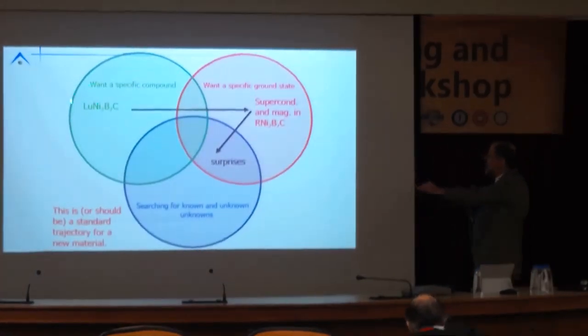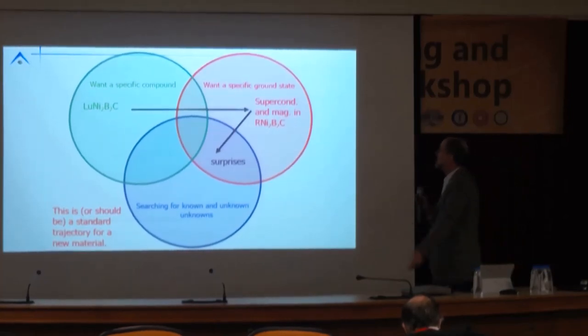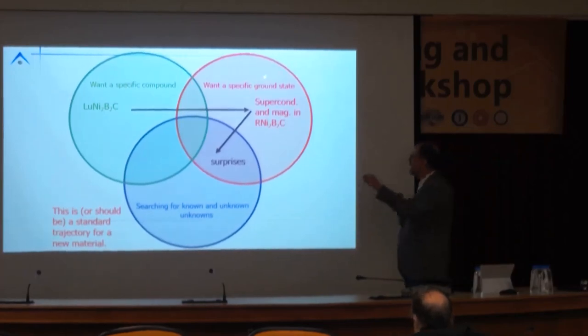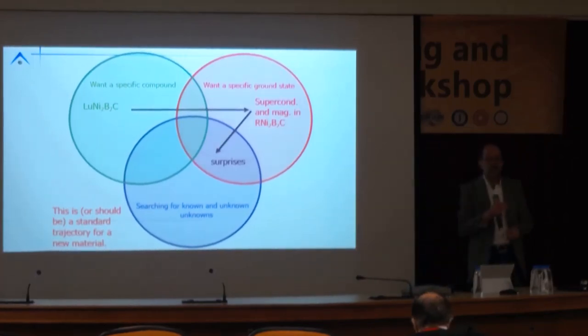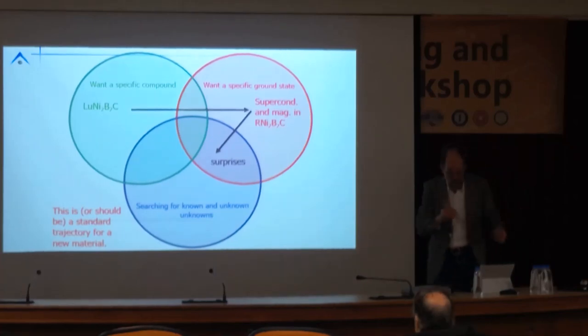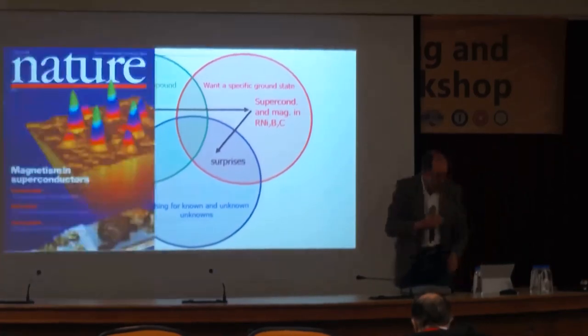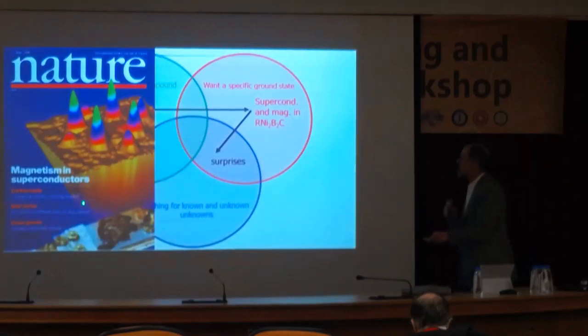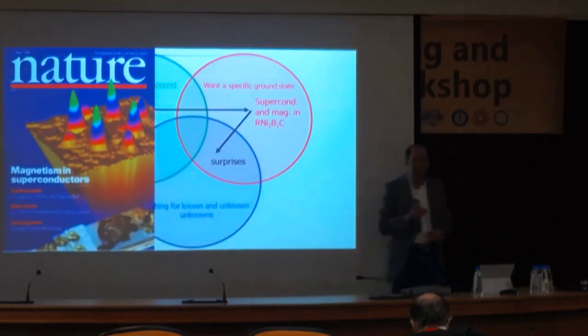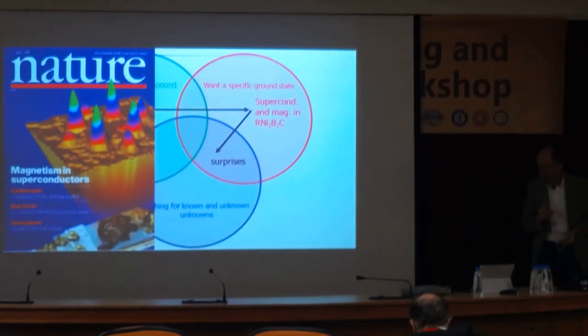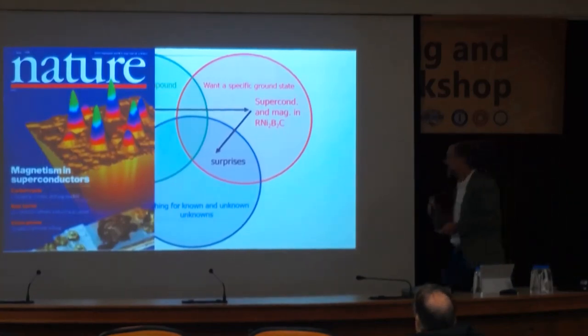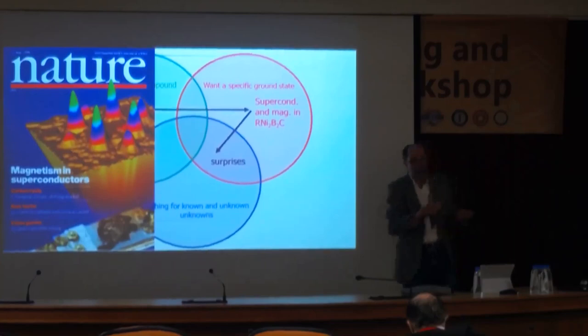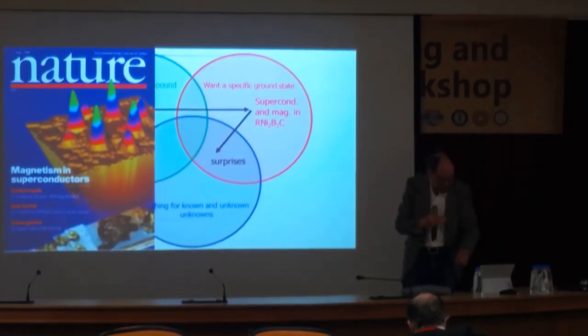So, we have a progression. We wanted a specific compound, lutetium nickel boron carbon. Once we had it, we could generalize and look at the interaction of superconductivity and magnetism in all of these materials, and as often is the case, this can lead to surprises or unknowns. In this case, the unknown was the discovery that in these materials, if you apply a small magnetic field, you could see, which at the time was one of the first examples, a hexagonal to square vortex lattice transition, okay? Due to basic non-local corrections for the square symmetry in the basal plane.